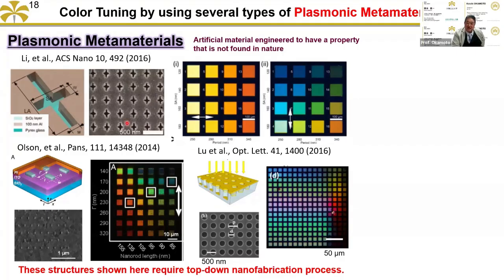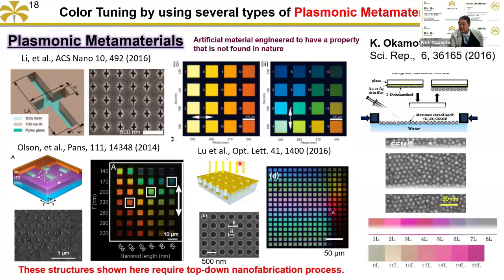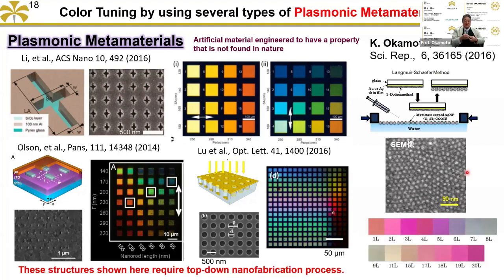Anyway, you have to make the very fine structure by E-beam lithography like that. But in 2016, we fabricated by a bottom-up process, just the self-organization of the metal nanoparticles. Then we transfer that to the substrate. Also, by the layer number, we can control the color. That's why such a very simple structure is also a metamaterial. It's an almost periodic structure, but a random structure is also useful for a metamaterial.